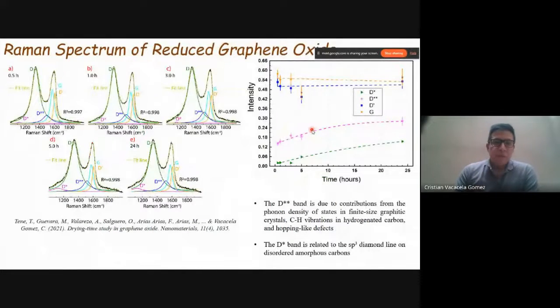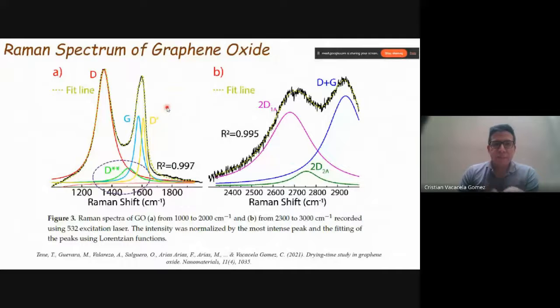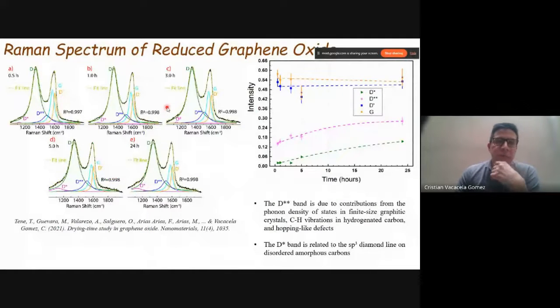Now, what happens here? The previous one, if you remember, was the Raman spectrum of graphene oxide. What happens if we increase the reduction time, just playing with the reduction time, independent of the chemical agent used for the reduction process? Look here, again we have the D, G, and D prime peaks, in all these spectra from 0.5 hours of reduction to 24 hours of reduction. Then what happens here? We identified the D star in the graphene oxide, but once the reduction process starts, an extra band starts to appear.